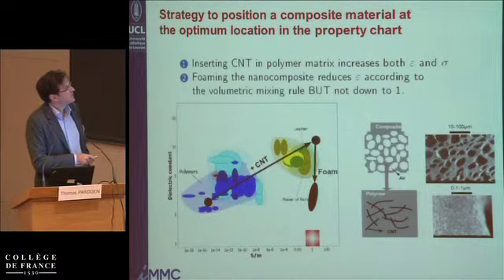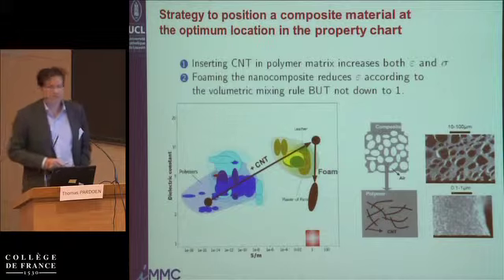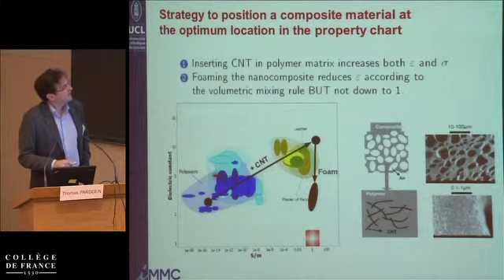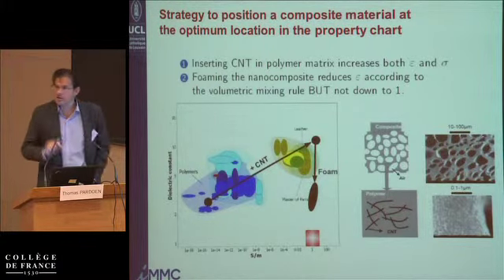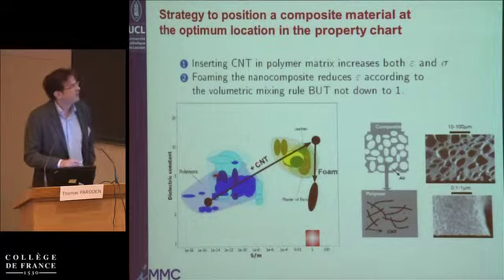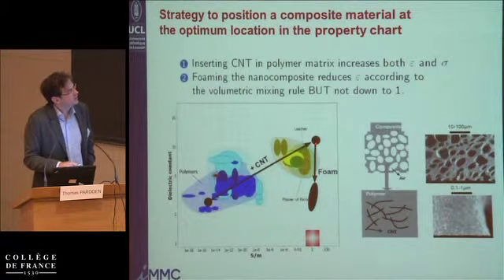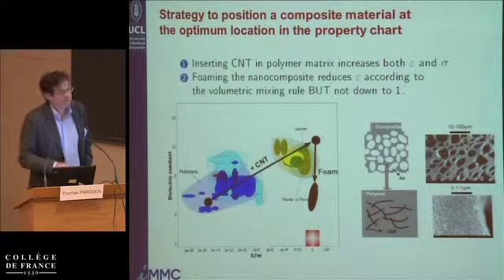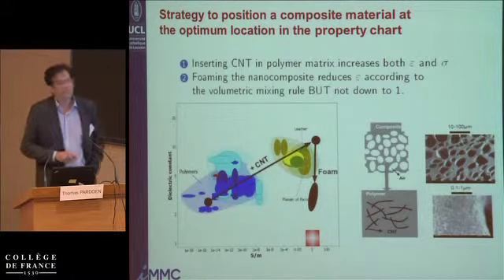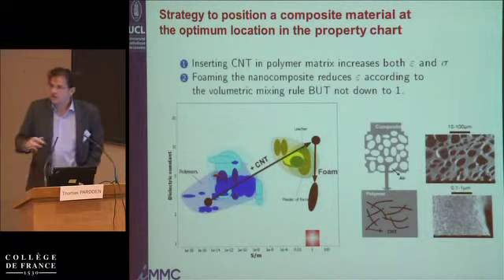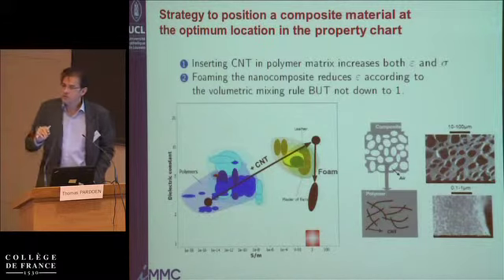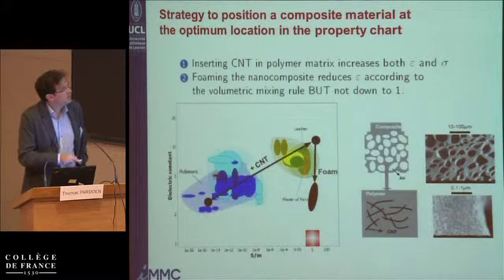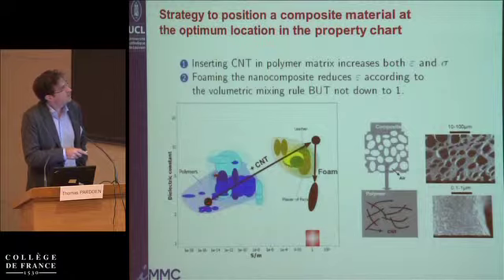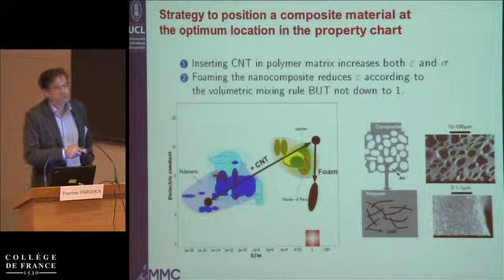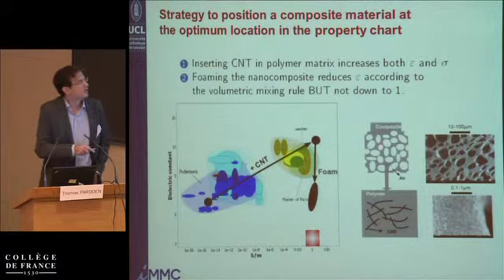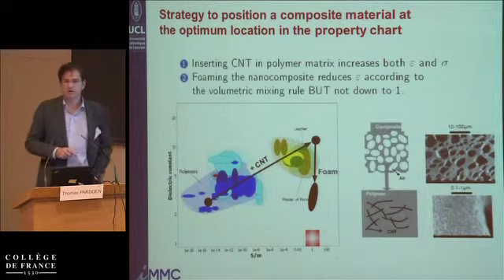We started with polymers, which have a low dielectric constant, and added the right amount of carbon nanotubes in order to increase the conductivity in the range of a Siemens per meter, which means about 1% or less of carbon nanotubes, so not a lot. And you need to control this very well. Unfortunately, when you increase the conductivity by introducing carbon nanotubes, you're getting a higher dielectric constant.